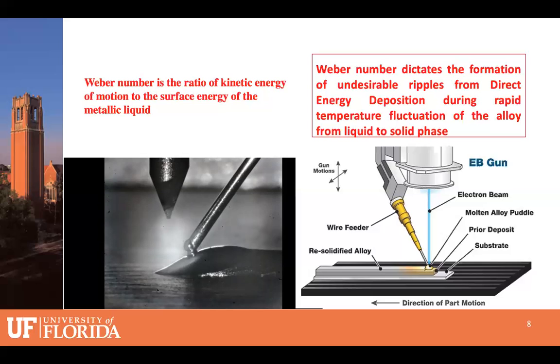The formation of ripples can be minimized by optimizing the motion of the platform. The optimal condition is given by a dimensionless group called the Weber number, which is the ratio of the kinetic energy of the motion of the platform to the surface energy of the liquid metal in contact with the ambient atmosphere, which might be typically nitrogen or argon, for example. This means that we need to have an accurate knowledge of surface tension and other properties, in fact, which will come into play, such as density, viscosity, and thermal conductivity.